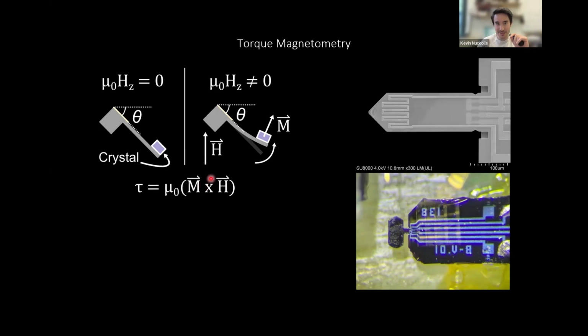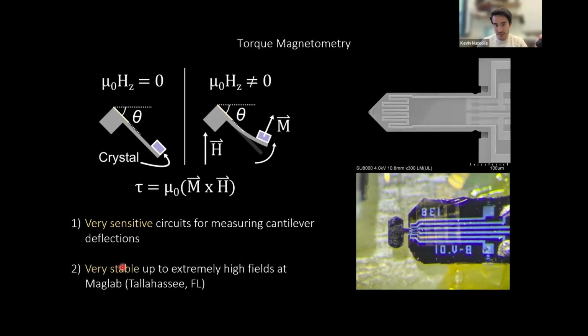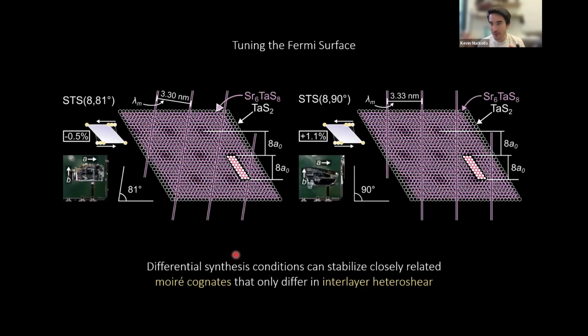The de Haas-van Alphen oscillations are oscillations of the magnetization, so we can read these out through torque magnetometry because we have really sensitive circuits for measuring the deflections of these cantilevers, and we have very stable setups that are stable up to extremely high magnetic fields, as we were able to use at MagLab at Tallahassee, Florida. So we did a bunch of these experiments, and there were a couple that stood out to me as particularly incisive probes of the Fermiology. So one of these experiments was that we had different crystals grown from different chemical synthesis recipes that had Moiré superlattices that are super similar.